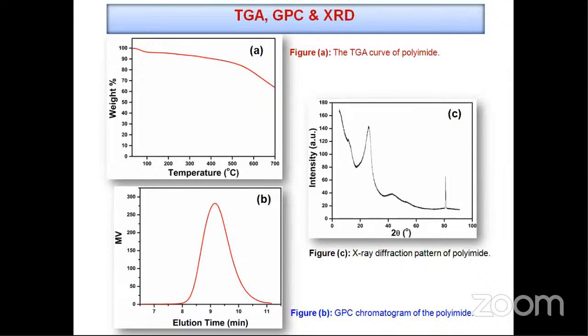Now the thermal stability of the polyimide was determined with the help of thermogravimetric analysis. This is the TG curve of the conjugated polyimide. Here the first weight loss at around 100 degrees centigrade corresponds to the loss of solvent molecules trapped inside the polymeric backbone, and the final weight loss started at around 480 degrees centigrade, which corresponds to the decomposition and degradation of the polymeric backbone. So this polymer is thermally more stable than its monomers.